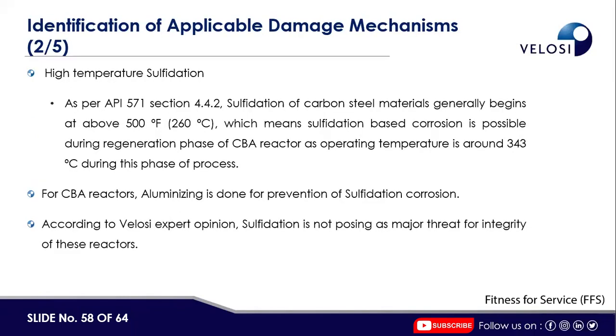High temperature sulfidation, as per API 571 section 4.4.2: if the operating condition of a carbon steel is above 260 degrees Celsius, this damage mechanism is applicable. For CBA reactors, aluminizing is done for prevention of sulfidation corrosion. According to expert opinion, sulfidation is not posing a major threat for the integrity of these reactors.